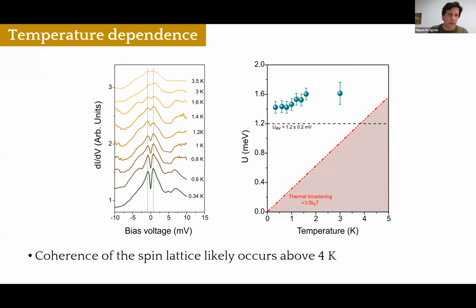Okay, so we have, of course, carried out the temperature dependence. Here I show you a set of curves taken in the same location, where we increase the temperature from 300 millikelvin up to close to 4 Kelvin. You can see that of course the resolution gets worse and worse, and basically there is a moment at which we are unable to resolve these two peaks.